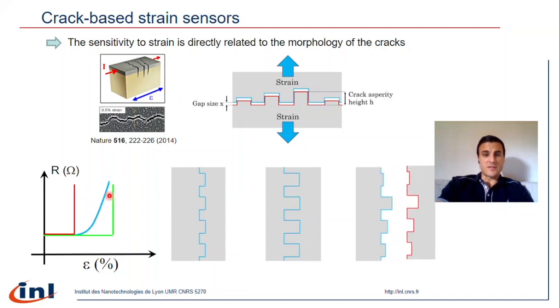To increase sensitivity, you have to increase the slope here of the curve by reducing the standard deviation on the size of the asperities. And if you want to shift the curve to the left, to the low strain levels, you have to reduce the average size of the grains within the crack.